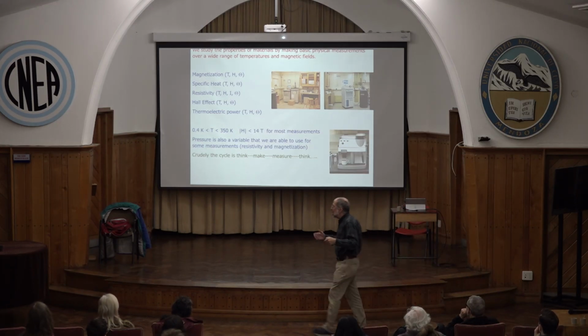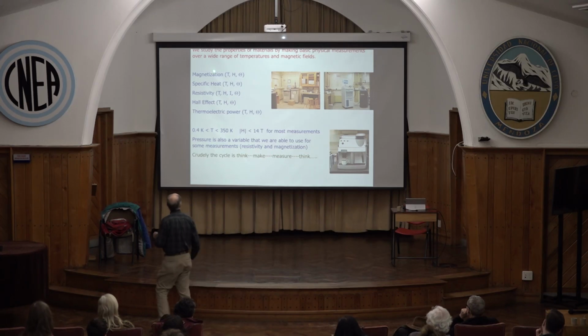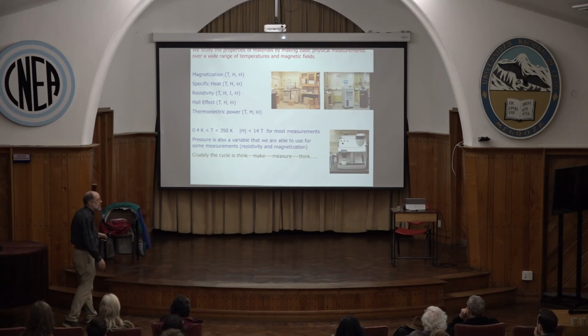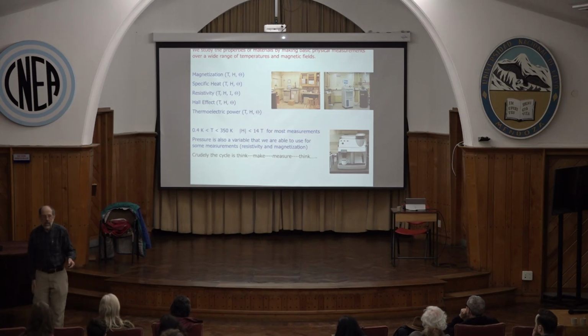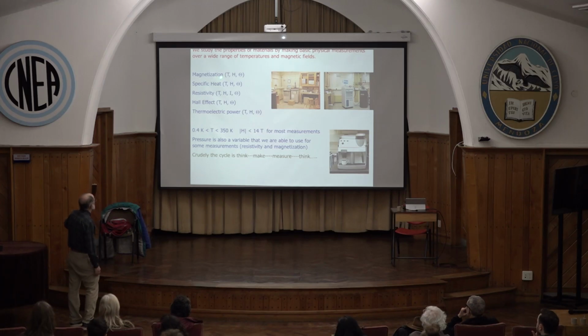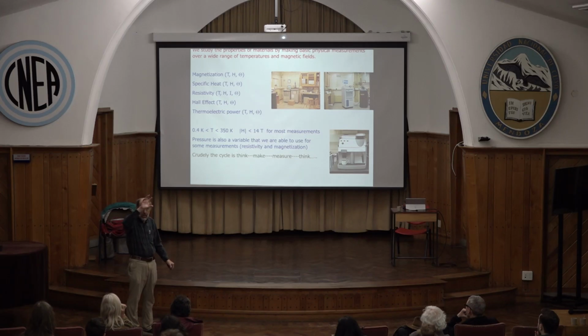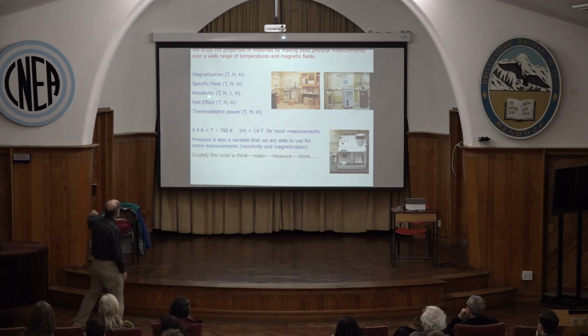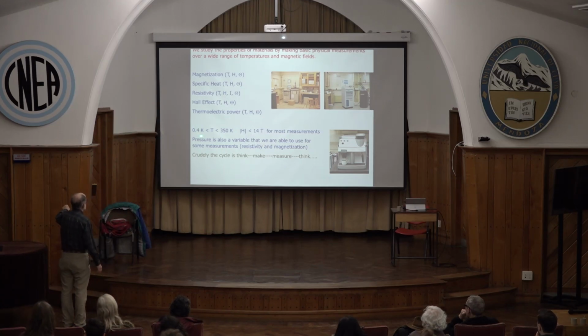Well, in my group, we try to study the basic properties. So these are quantities, some of which you teach in your introductory physics, chemistry, thermodynamics courses. We measure magnetization as a function of temperature, field, and, since it's a single crystal, the angle that we're applying the field along. Specific heat, resistivity, Hall effect, thermoelectric power, thermal expansion, magnetoresistance. We generally measure between 0.4 and 350 kelvin, although we can go up to 1,000, and we can go down below 0.4 if we have to.